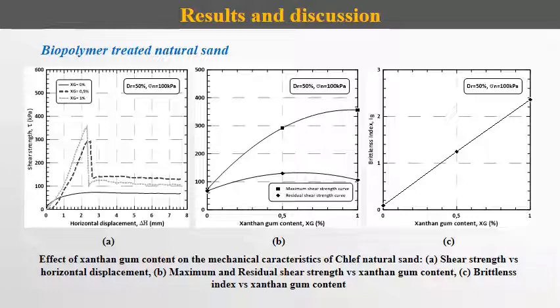This increase in resistance is due to an increase in soil rigidity. However, xanthan gum treated specimens have shown a decrease in residual strength after the peak shear strength due to the stiffening of biocemented samples.